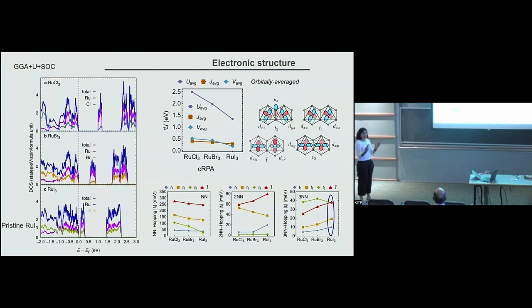However, the gap reduces as you go into larger halogen atoms. And in the case of the pristine ruthenium iodine, you are really on the verge of a metal-insulator transition. So in our case, if we are in the pristine one, it should in fact be an insulator. And the question is, what kind of spin exchange do we expect for these materials?